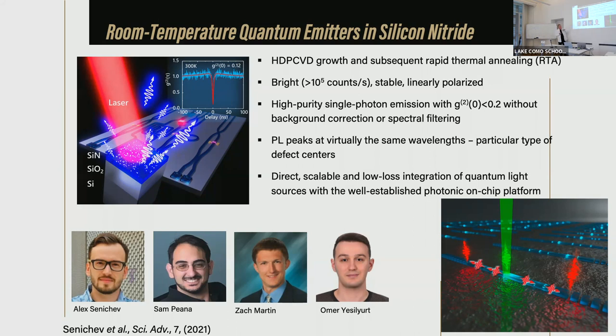We actually obtained really bright single photon sources, to our surprise. So with purity, again at room temperature, below 0.2 in most of the cases. In many cases, they're going below 0.1. All the photoluminescence peaks tend to be grouped around the same spectral range, indicating that this is one particular defect or vacancy, whatever, which we still don't know yet, which is responsible for this emission. And of course, this is access to a scalable approach where all the industry already exists. You could make really millions of structures on the chip, and that makes it exceptionally attractive.